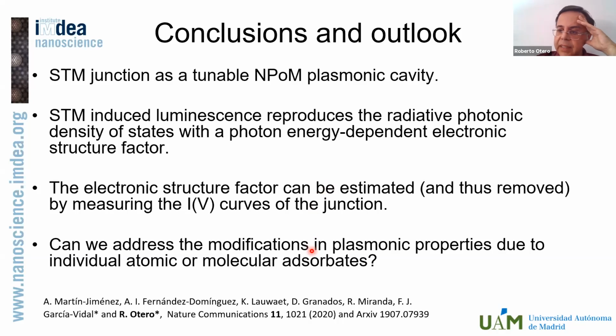And that opens a lot of interesting questions, such as, now that I truly know what I'm measuring, and in particular, now that I know how to avoid all these problems with the electronic factors, I could place molecules in between, I could place 2-dimensional materials, I could place graphene nanoribbons and so forth, and study their effects on the plasmonic response of the cavity in an individual way. We actually got these results published recently. You can check for further details there and in the supporting information.